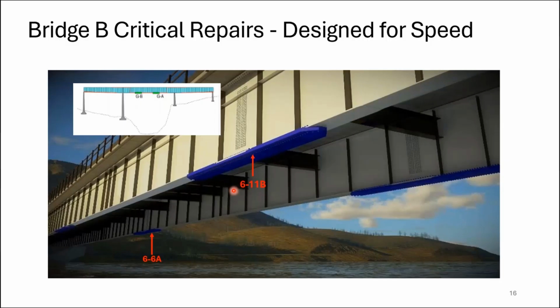The 2 points that I have highlighted here are the 2 places that we had cracks. To provide a little bit more comfort with reopening the structure, we did the adjacent girders at the same locations. These locations were adjacent to the field splices in the girder, and so that needed to be accounted for in the design. Because we had weight restrictions on the bridge, these plates also needed to be under a 9,000 pound limit, so that the crane could move the plate out onto the bridge and then suspend it underneath. Because we were so weight restricted by the limits of the bridge, we also went with an underslung design so that the crane could hold the plate in place while they were installing it without any additional equipment needed.